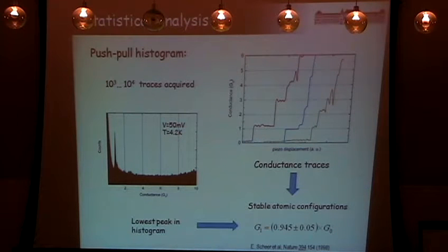In our case, this last peak was at a conductance value of 0.94 G0, which is in good agreement with both earlier calculations and experiments. Just would like to show this paper for this.